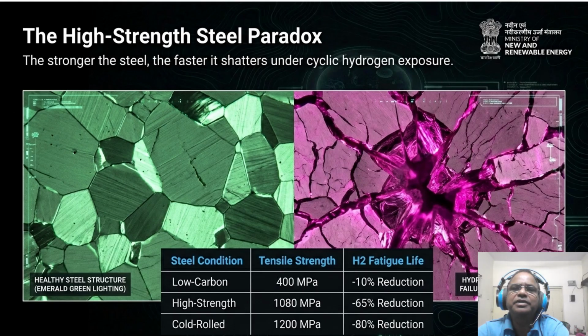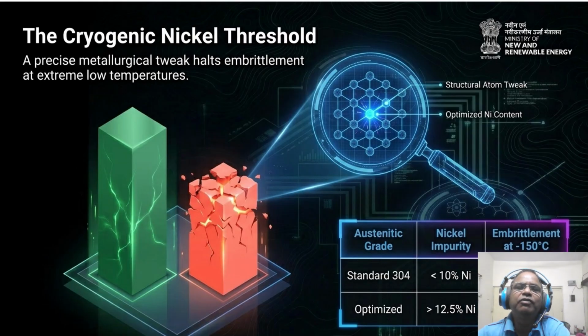in high pressure dispensers. However, there is a metallurgical silver bullet when we look at the cryogenic threshold of specific alloys, and our slide is on this specialist topic of the cryogenic nickel threshold. We have found a precise metallurgical tweak that changes the game. Look at the two bars. The green bar on the left represents optimized alloy, while the red crumbling bar represents a standard 304 steel at minus 150 degrees centigrade. The secret is nickel content, as shown in the table.